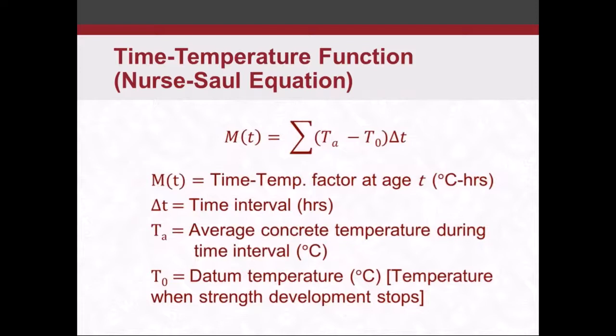So here's the Nurse-Saul equation. If you look at this, it's basically a formula for area under a curve, right? M of t is your time temperature factor at age t. Delta t is your time interval. Normally, when we're doing this maturity testing, we're looking at either 1 minute or 15 minutes, depending on how long we're carrying out the test. So this delta t is usually a 1 minute or a 15-minute interval. T sub A is the average temperature during that time interval. So we know what the temperature is during that 1 minute or 15-minute time interval.